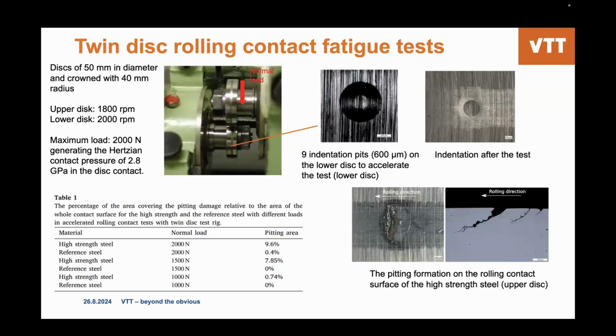And to accelerate the fatigue test, because if we don't do so, that will run for years, because it is quite good material, I would say, 9 indentation pits were made at the lower disc with 600 micron. And here, this picture shows the indentation after the test. And this image shows the pitting formation on the rolling contact surface of the high-strength steel.